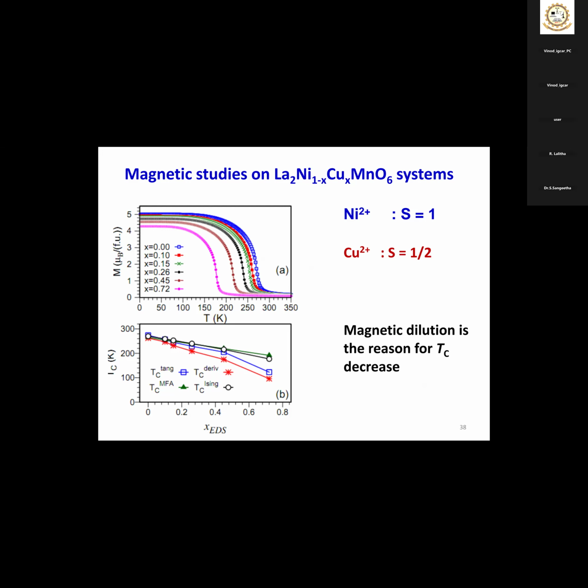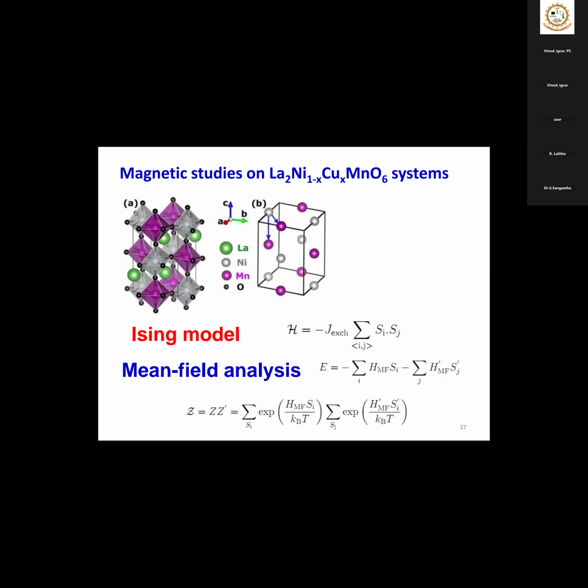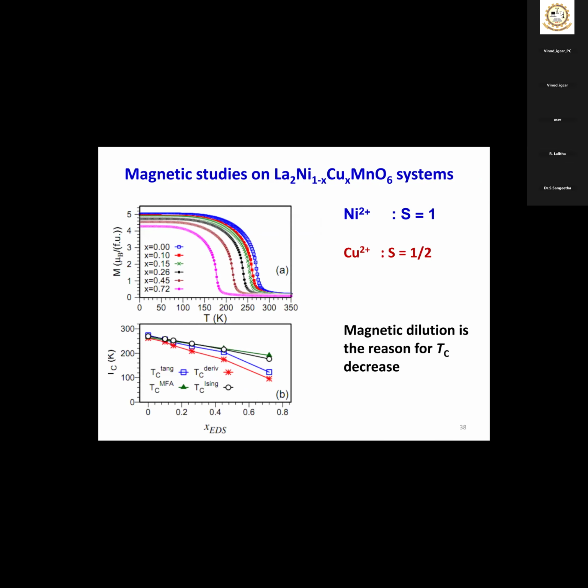You can see that nickel has spin S equal to 1 and copper has spin S equal to half. Here J is the exchange interaction. I have considered all the exchange interactions identical, irrespective of copper content. Only I varied the spin part, because nickel has S equal to 1 and copper has S equal to half. I did the calculation, and the result is agreeing more or less with the experiment.